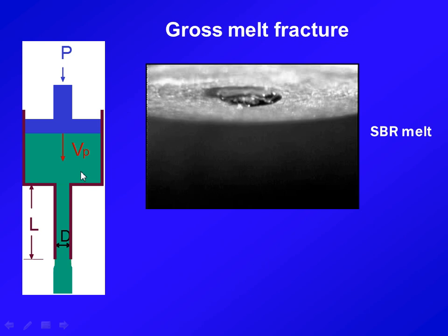So here's what you do. You get hold of a rheometer. You push your material into the die, which means the material has to be squeezed from there to the die. And then you sit there and wait, just do nothing, until this sample already forgot it went through some dramatic history coming in. Every molecule is all relaxed. And then you start your experiment. And that's this movie.